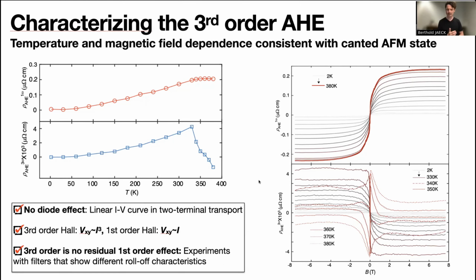Of course, one can argue that first order, second, third order Hall effects can often be related, for example, through some diode effects that induce a higher order response. There could even be some self-induced Joule heating that can lead to a self-induced orbital third order response. To exclude all these other possibilities, we have conducted various types of control experiments. So we find linear IV curves in two-terminal transport, which excludes any rectification effects from, say, a diode.